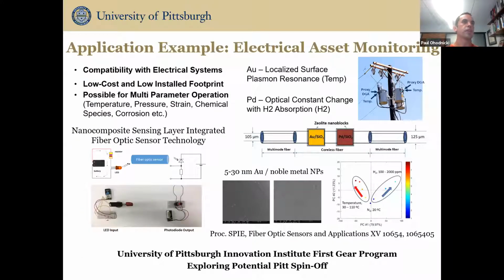If you take an optical fiber sensor, and you integrate gold nanoparticles in a matrix and palladium nanoparticles in a matrix, we can take advantage of both of the two types of sensors that we just talked about. We can use extremely low-cost photonic-based measurement systems, a low-cost LED, a low-cost photodetector. This can be integrated onto a fabricated device in the future. This allows us to measure signatures of hydrogen as well as temperature at a cost which starts to be compatible with deployment in actual distribution transformers as well. So this can start to give some visibility into assets which were previously not possible.